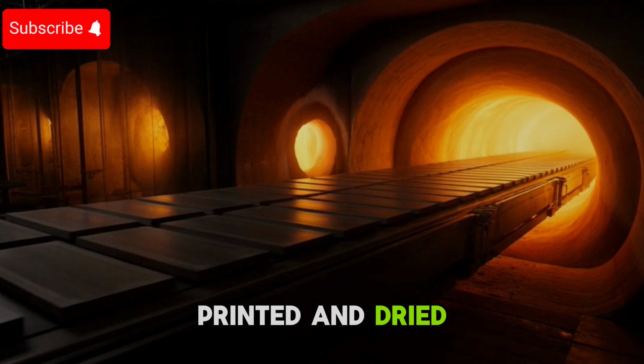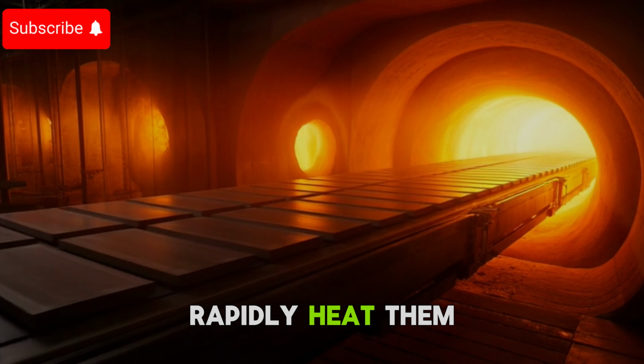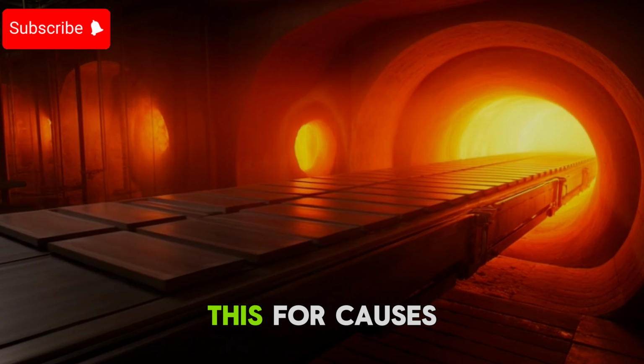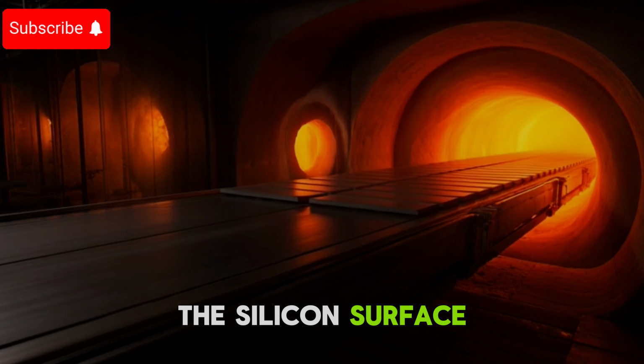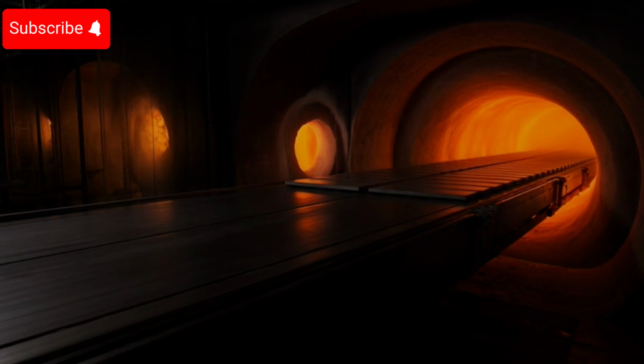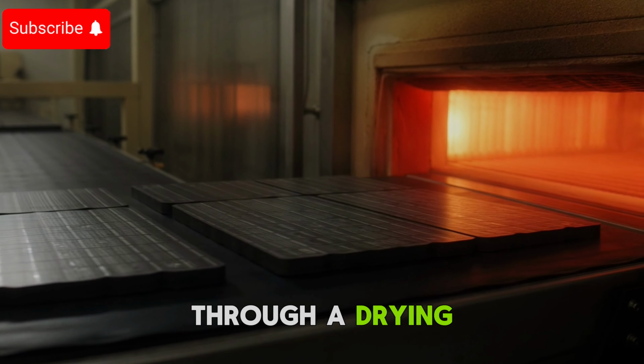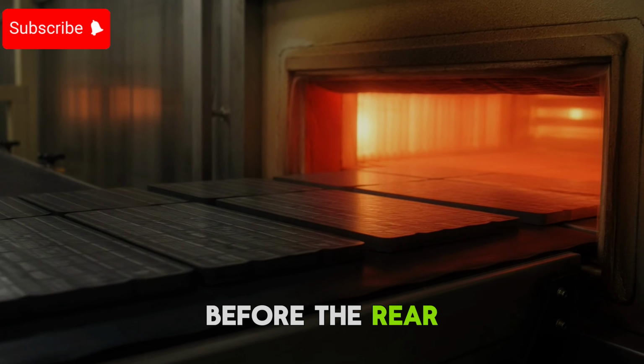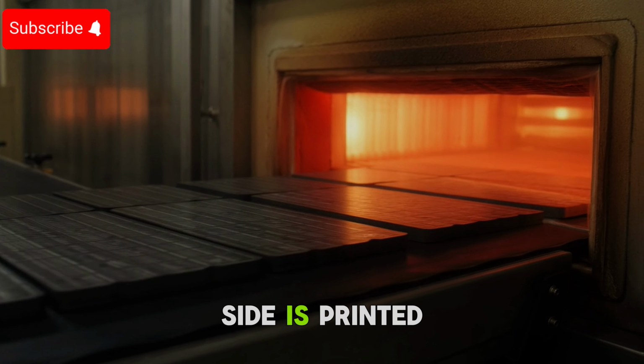With both sides printed and dried, the cells enter the firing furnace. A long tunnel rapidly heats them to around 800 degrees, then cools them quickly. This causes metal paste to fuse permanently to the silicon surface, forming low-resistance ohmic contacts. After front-side printing, the cells pass through a drying oven that fixes the paste in place before the rear side is printed. This intermediate drying step ensures the front contact pattern is not disturbed during rear metallization.